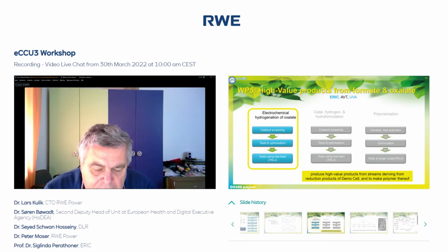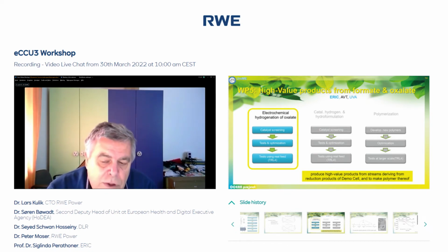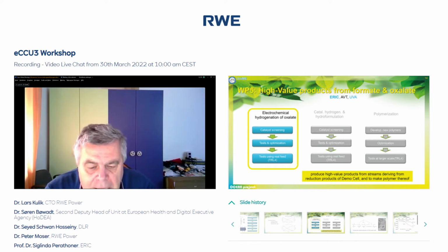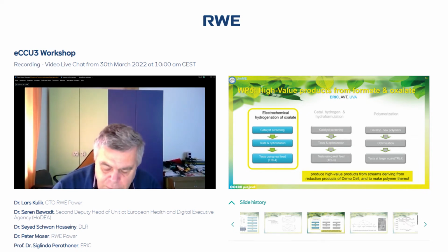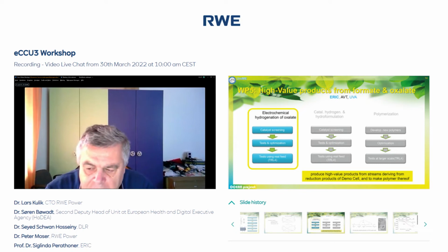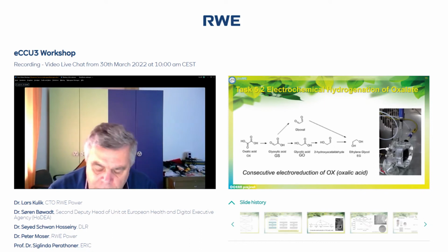Initially, the aim was to arrive at ethylene glycol because, of course, it's quite an interesting raw material. But in the end, if you analyze the cost, because you need more electrons, it's more difficult to obtain. Also, if you compare the added value of the product, the possibility to make it, and the consumption of electrons, which is a cost, then you see that glycolic acid is probably the best combination and best target. And you see on the right some of the lab-scale reactors that were used in this case.